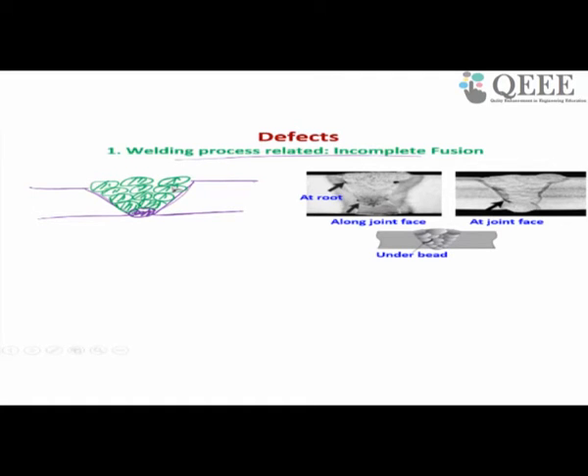If it somehow does not fuse at some region, for example, after each pass you get a slag layer on top of it. Then you have to remove that slag layer and deposit the second pass. Again you will have a slag layer, you remove that slag, and deposit the third pass. By chance, if some slag is retained in the material, then in that region fusion will not happen. Or if your heat input or welding process is not perfect, then in some region fusion may not happen. This is called incomplete fusion.